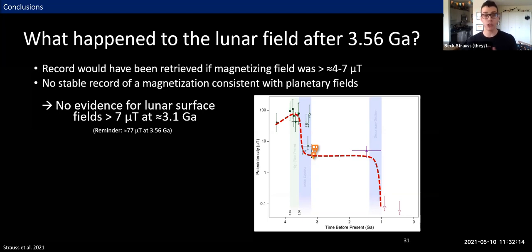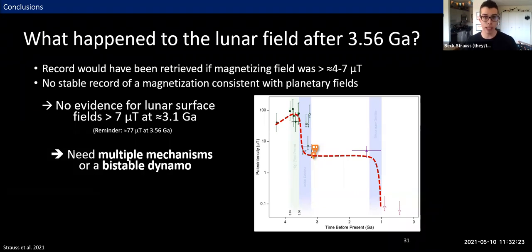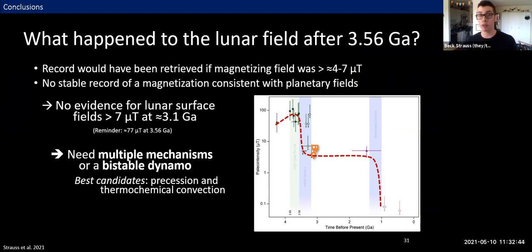As a reminder, the field was an order of magnitude stronger at about 3.56. So this is a decline of an order of magnitude over around 400 million years. In order to explain this change from a high field state to a weak field state, we need either multiple mechanisms of field generation or some kind of bistable dynamo that could have been stable in both configurations. Among the available candidates, we currently think the most likely ones are a combination of precession and thermochemical convection. And what this could look like is a precession generated dynamo driving the existence of a strong magnetic field until the moon's gravitational state as it moved away from the Earth was no longer conducive to sustaining it.